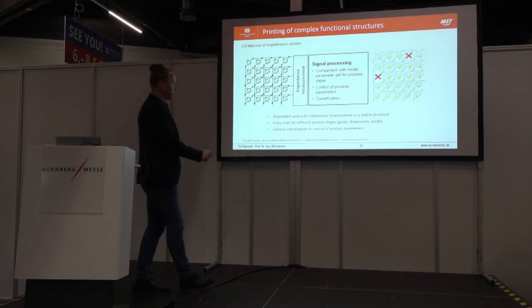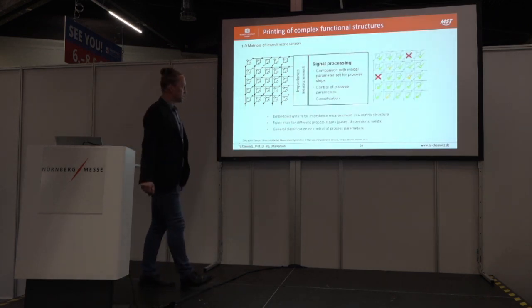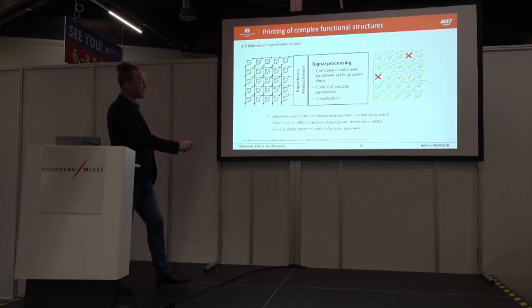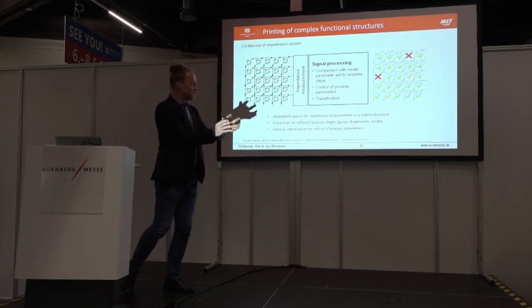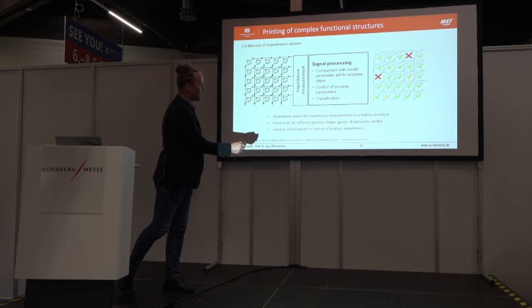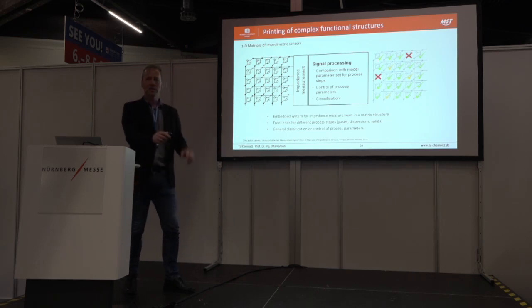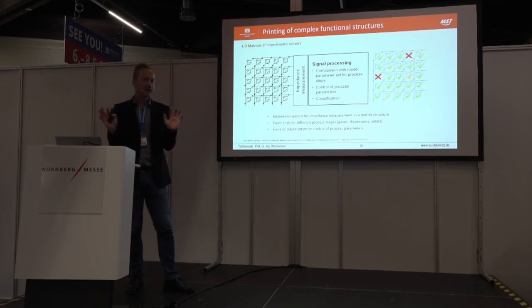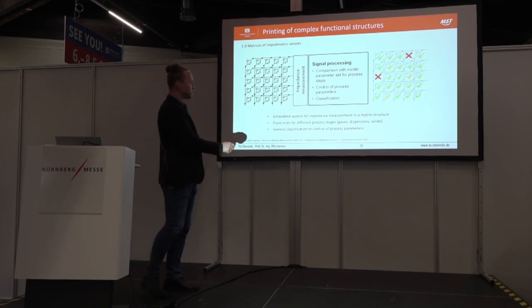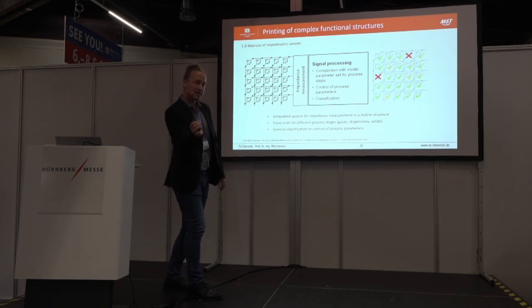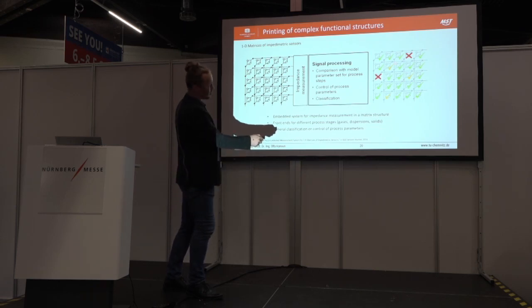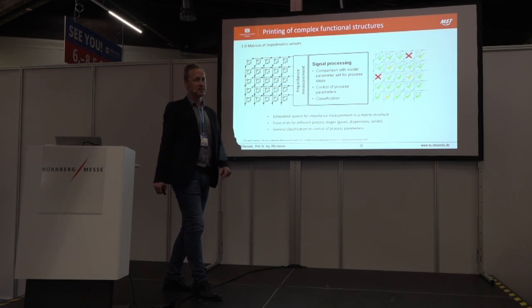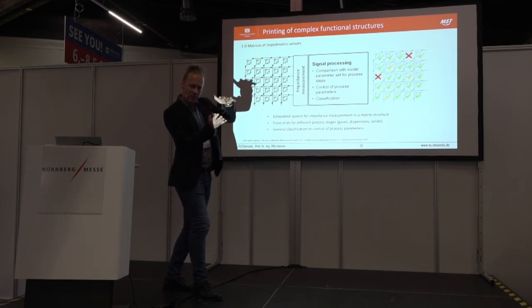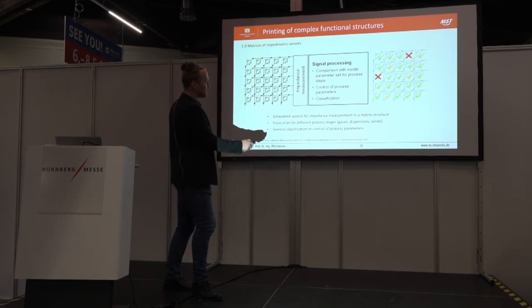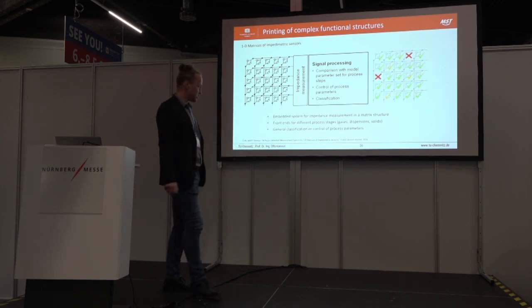What is the idea? We have here our impedance-based measurement. We are able to measure each of these matrix elements in a way that we can say, okay, this and this are okay, and the fourth in this line has some kind of problem. And my system maybe can adjust process parameters. Maybe here you see the yellow arc. It's maybe in the range of the tolerance band. So here you can adjust the parameters, and this one you exclude from the further production steps.